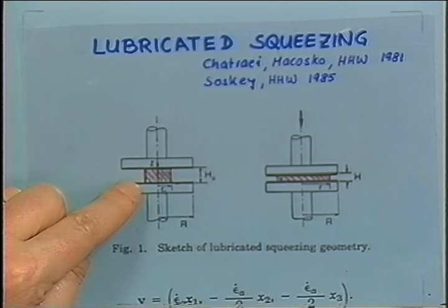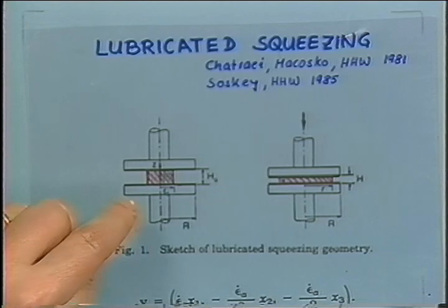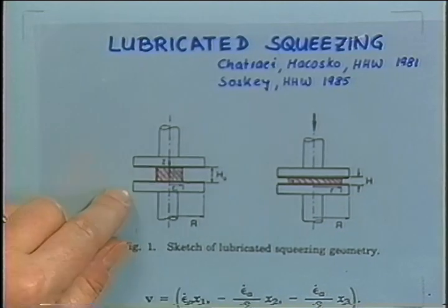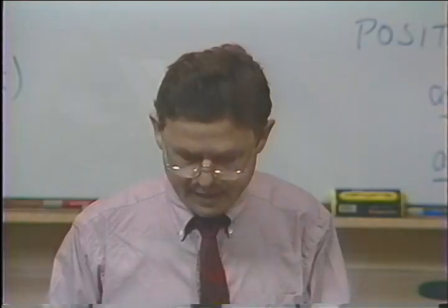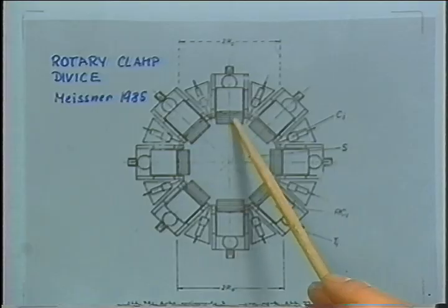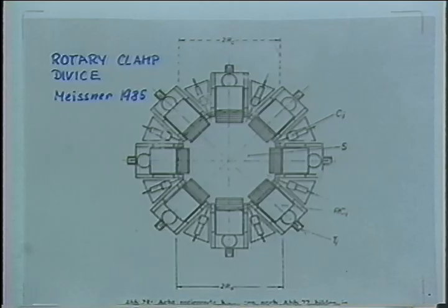Remember, we looked at step strain data of Osaki's group in shear and found it very informative, doing step strain at various shear strains, going from the linear behavior to large strain behavior. Now, with this device, we could do step strain at high temperatures and at large deformations, and then get the complementary functions to the step strain in shear data. So that's very helpful. If you would take this type of geometry here, the rotary clamp, and would try to introduce a step strain, then you would break the sample. You would just rip it apart very quickly.